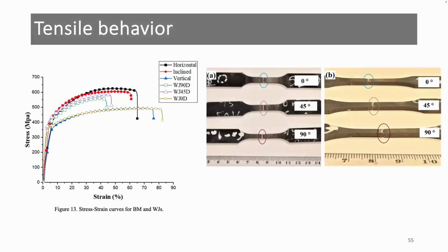Regarding the tensile behavior, we find that the vertical one here is the WJ0D, the weld joint with parallel direction, showed very similar stress strain curve as the base metal. However, here in the 90 and 45 degree, there was a reduction in the strength and ductility.